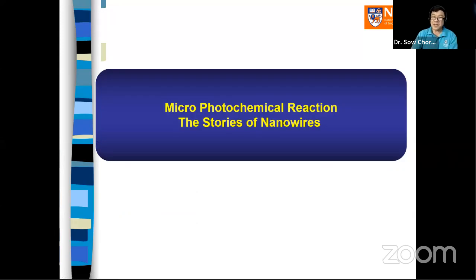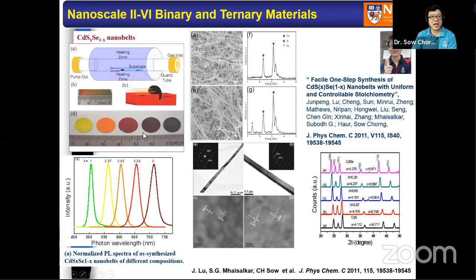You can use this focused laser beam as a way to do localized chemical modification. Now I'm a physicist, so I'm not a chemist. But you can try to use this focused laser beam as a means to tune the chemical stoichiometry of your nanomaterial system. So what do we try? We play with this particular system called CdSSe, the ternary compound. It's actually in nanowire form. And my student, Jin Peng, learned to grow them with good control of the chemical stoichiometry.